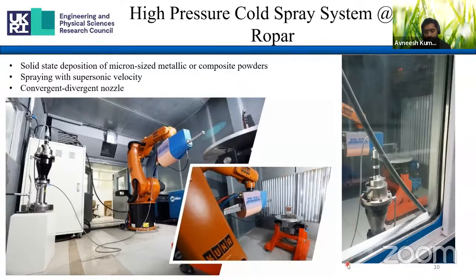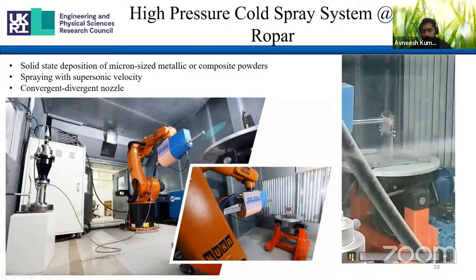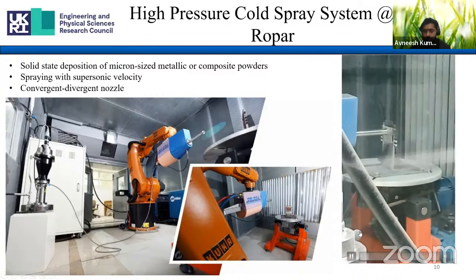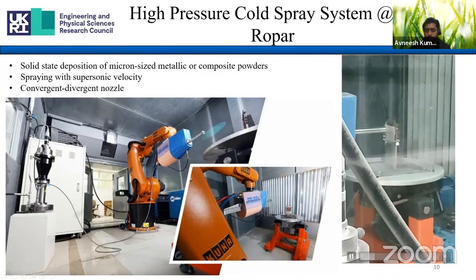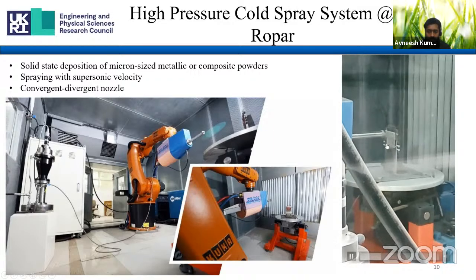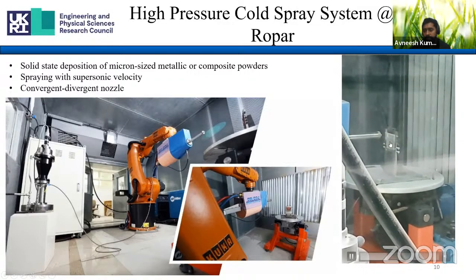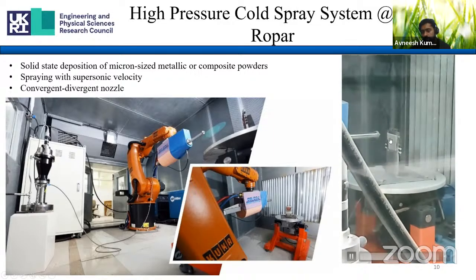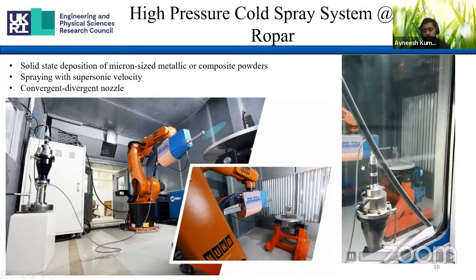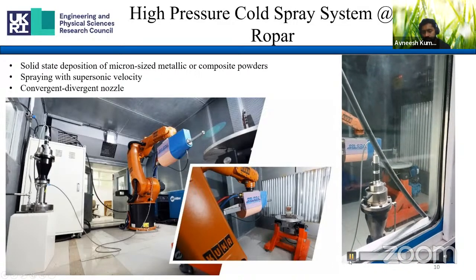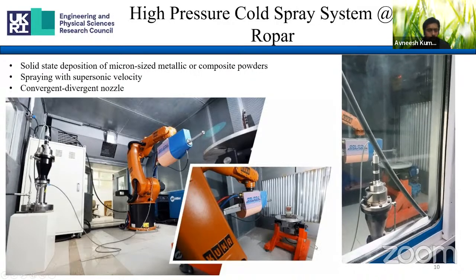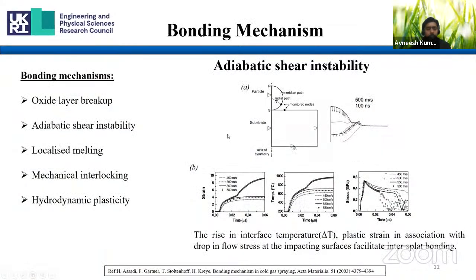While spraying these powders, I tried to capture this video, which you can see. This is titanium we sprayed on an SS316L substrate, and you can observe the flashing jet. That is because titanium is pyrophoric in nature. After that, as the particle strikes the substrate, it forms bonding, and that bonding can be described using several bonding mechanisms.